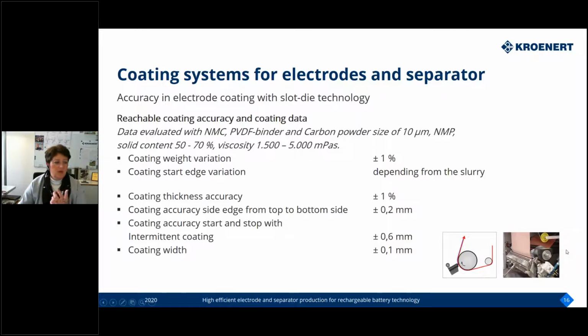This is realized with special alignment of the substrate, also with sensor systems. And here we can give a guarantee of 0.2 millimeter from one side to the other side. Accuracy in start and stop operation with the die during intermittent coating is plus minus 0.6 millimeter, and the accuracy of this we can also give in a very good range, as you see here.